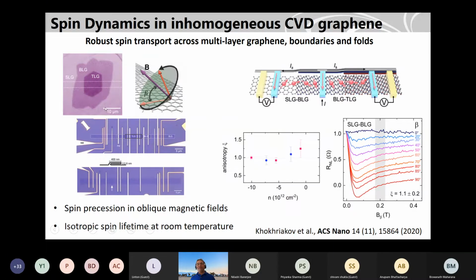And what we surprisingly found out, so what we did is called a spin dynamics experiment, where we measure the Hanle effect, a spin precession experiment. We are applying a magnetic field, so spins are precessing, and we do this at different angles. By doing that, you can fit and find the anisotropy or other things developing in the system. Because there are some systems where you will find lots of anisotropy in the spin relaxation, because they can have high spin-orbit coupling or something like that. But in the graphene system, we don't find anything at room temperature. It's very isotropic, around 1, and that's quite good for spin interconnects.